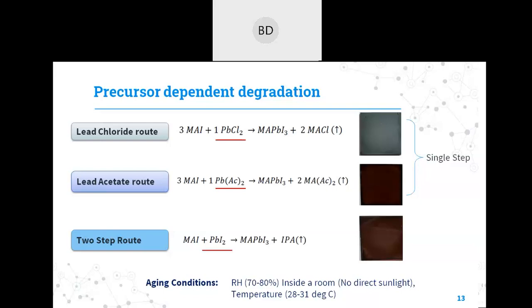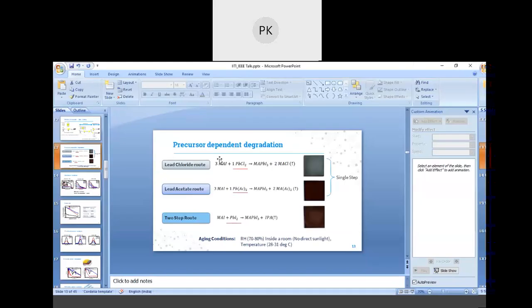Okay, sir. So is there any method to suppress this oxidation, like the transition from oxidation state 2 to 4 in the case of tin? The oxidation state of tin is its inherent property, so oxidation states cannot be changed. But what we can do is make it more stable. We cannot use tin as a complete replacement. What we can do is use some part tin and some part lead. So the structure can be made more sustainable and it can reduce some oxidation of tin. But inherently Sn+2 and +4 you cannot change. You can use some lead portion so that you make a good perovskite and reduce the probability of getting oxidized.